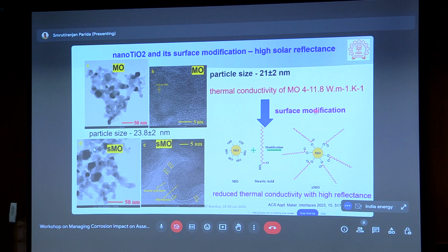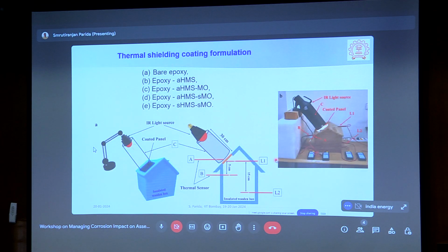thermal shielding coatings. So what we did is some surface modification to that, so that we can create a very thin layer around this TiO2, nano TiO2, a very thin, insulating layer created by chemical modification. And when you add this along with the hollow microspheres, the combined effect has resulted in a temperature shift of the order of 21 degrees.